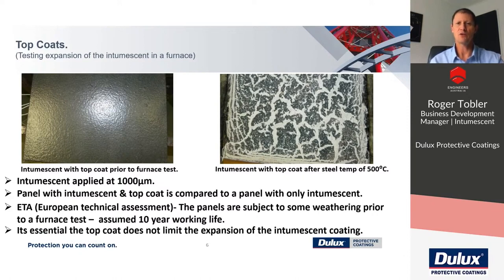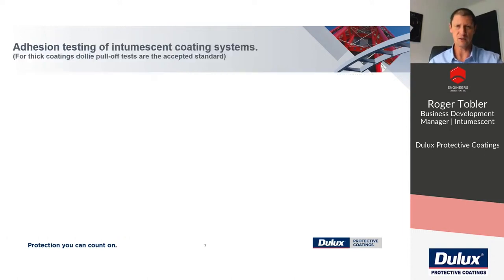It's really essential that the top coat doesn't limit the expansion of the intumescent, and without any testing of the top coats by the intumescent supplier, this can't be guaranteed. So this is really essential that top coats are tested.